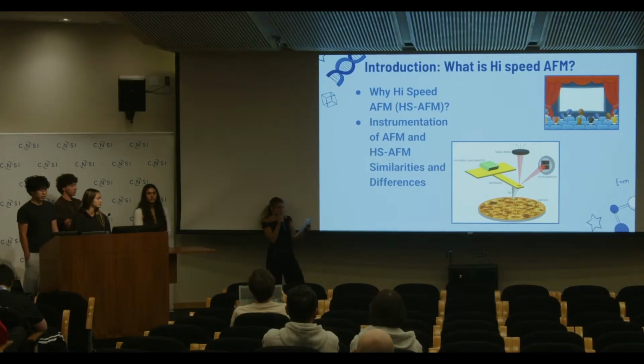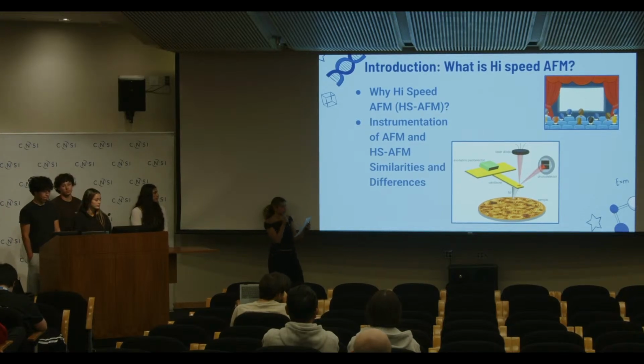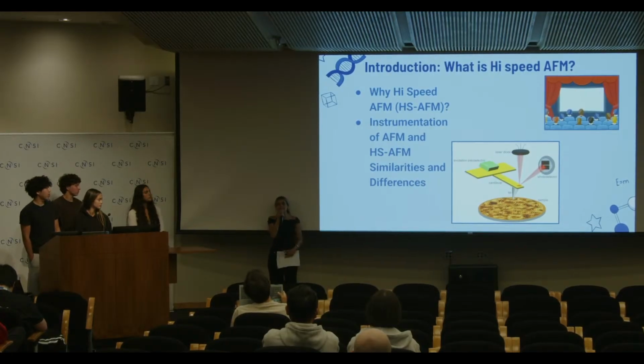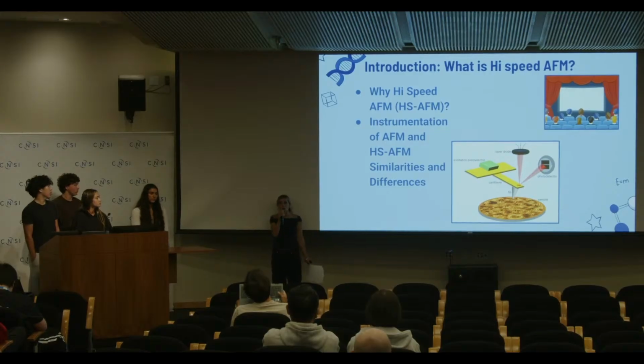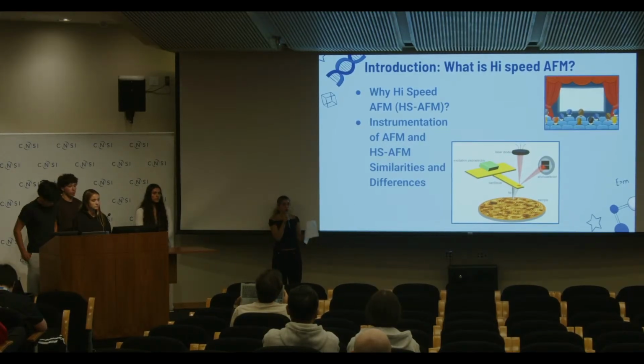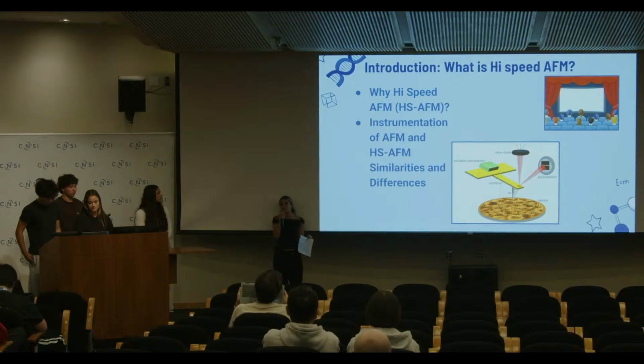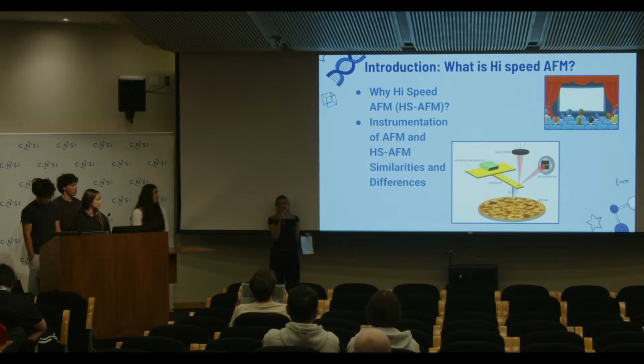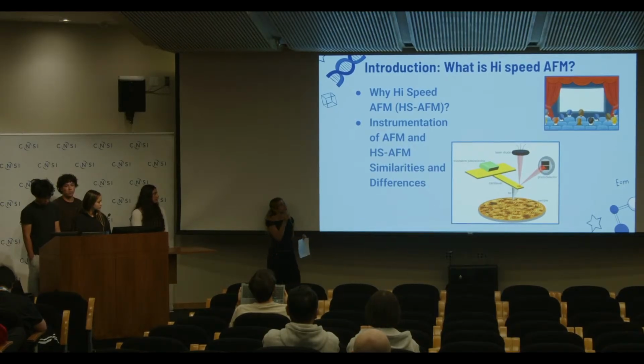And additionally, HSAFM allows imaging of wet specimens with nanometer resolution, capturing the fast motion of native proteins at the molecular level. And like all kinds of scientific measuring, it does have its drawbacks. In this scenario, there is a higher rate of damage possible to the sample because of how fast you're moving. There's also the spatial resolution is reduced, again, because of how fast you're moving, and it's more costly than the AFM. But it has made a lot of contributions to science and is really helpful in measuring samples, which Sophia is going to touch upon right now.